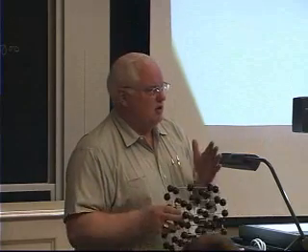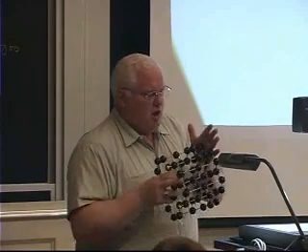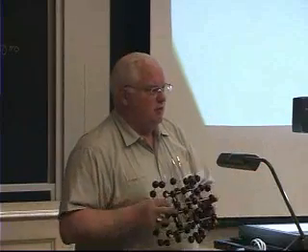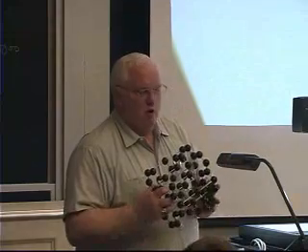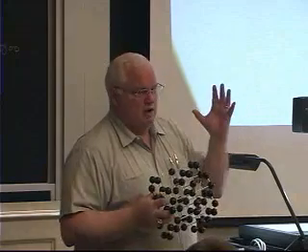Carbon and oxygen have an affinity for each other. That's why they form carbon monoxide and carbon dioxide. So on Earth, at atmospheric pressure with 0.2 atmospheres of oxygen, you would get a layer of oxygen on this one, and the one next to it would also have a layer of oxygen on it. So you're really sliding on carbon monoxides, okay? And they don't have a very strong, high surface energy. If you go through the Lennard-Jones calculation, they actually work quite well. You get up in space where you don't have a lot of oxygen, it turns out the strength of that bond was not so great. You'd actually just suck off the oxygen.